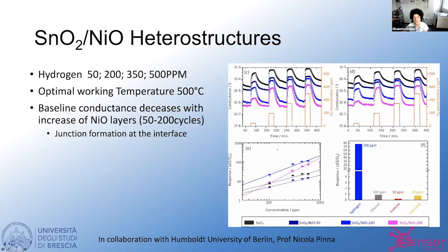What we can see is that we have a decrease in the baseline conductance as we increase the thickness of this nickel oxide layer. And we have the junction formation at the interface. And we have a very high optimal working temperature, which is 500 degrees C. And if we look at the response of this layer towards hydrogen, we can see that we have an increase compared to the bare tin dioxide material.